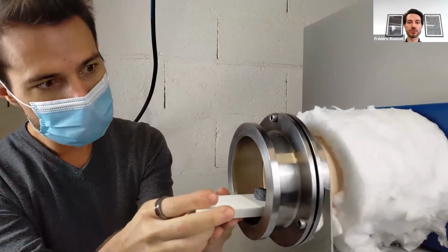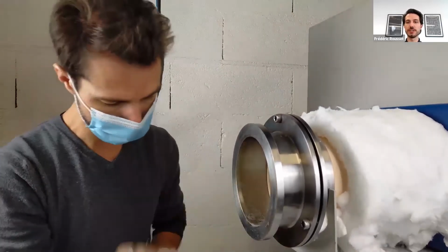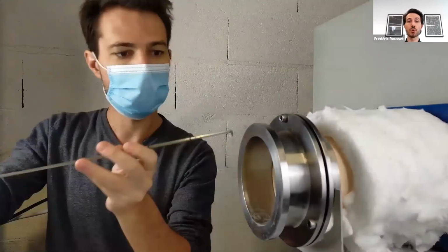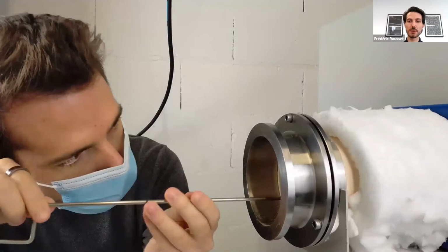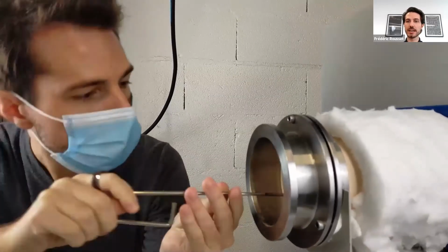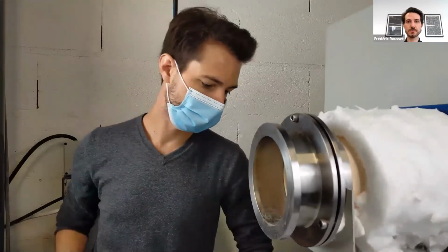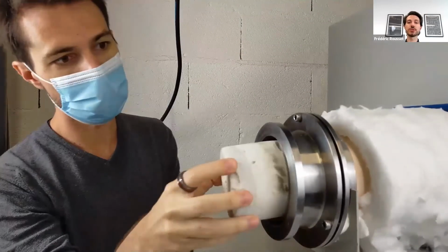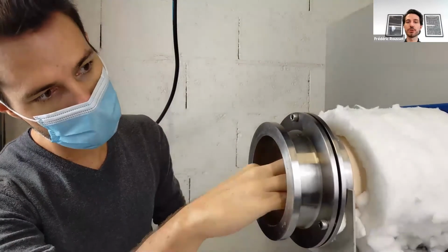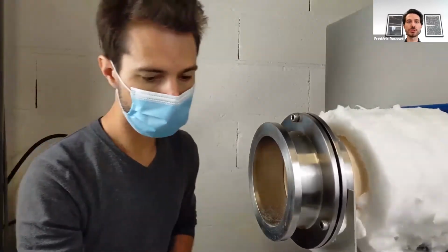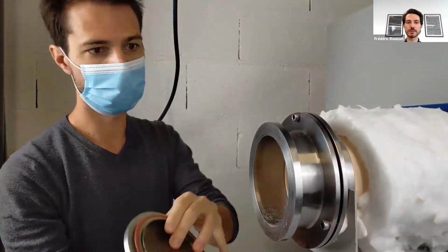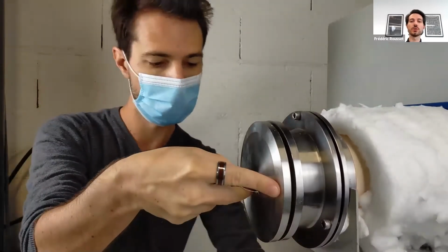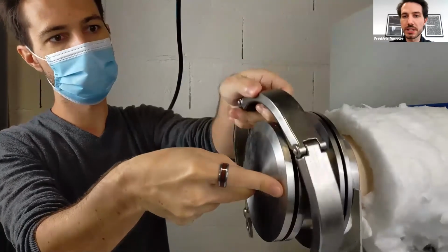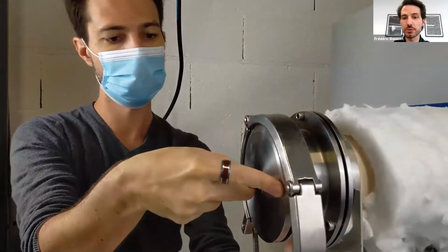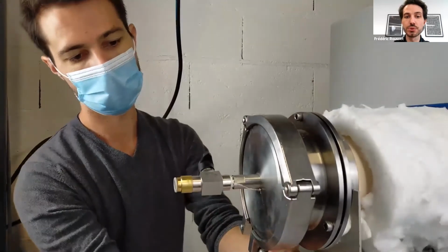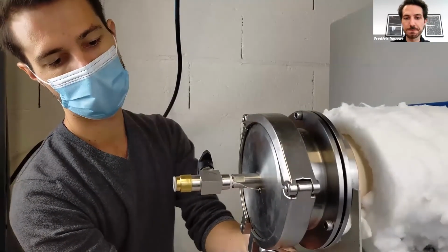For the metallic parts that you are using, you will need to have a flow of argon. So I'm going to put the piece at the center of the furnace, which is quite important. I'm going to put some thermal shields so that the temperature is even inside the furnace. And I can close it. When I'm closing it, it is mainly useful for the metallic parts, where you can put a flow of argon in it.